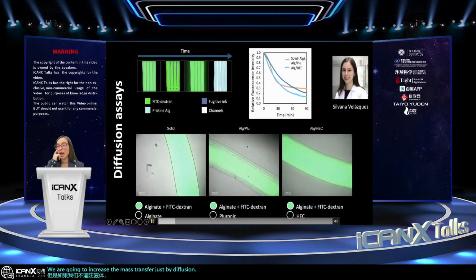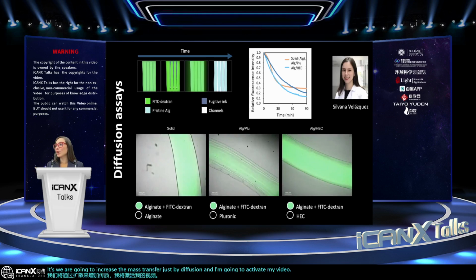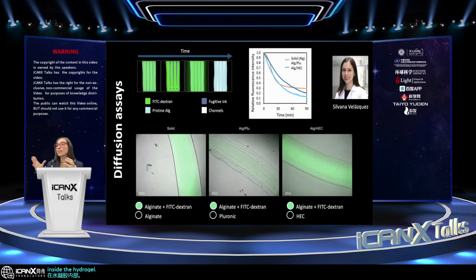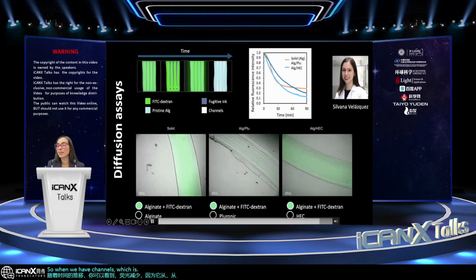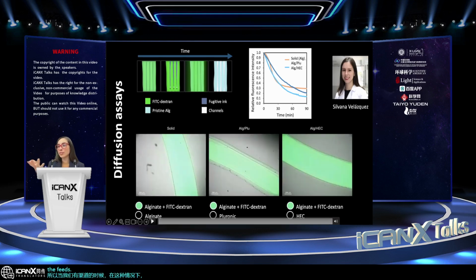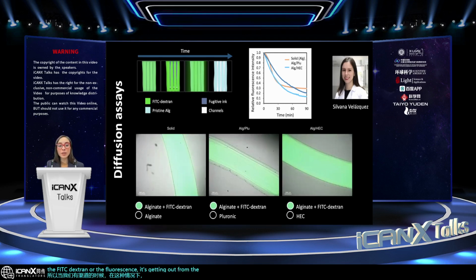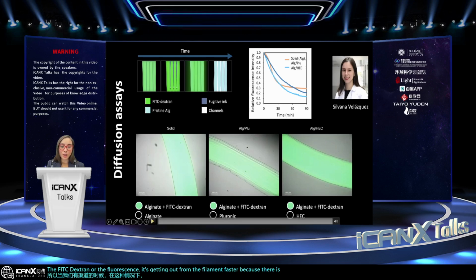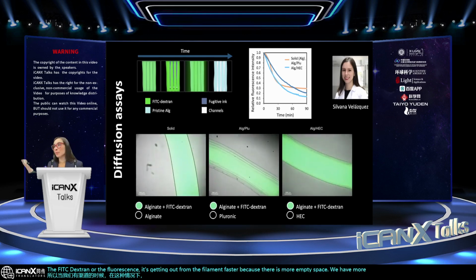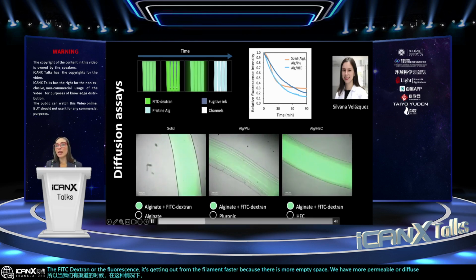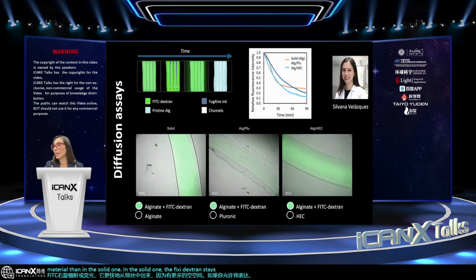And I'm going to activate my video here. So what we have here is FITC-dextran inside the hydrogel. And as time advances, you can see that the fluorescence decreases because it's diffusing out from the filament. So when we have channels, which is in this case and in this case, the FITC-dextran, or the fluorescence, is getting out from the filament faster because there is more empty space. We have a more permeable, or diffusible, if you allow me the expression, material than in the solid one. In the solid one, the FITC-dextran stayed within the hydrogel.